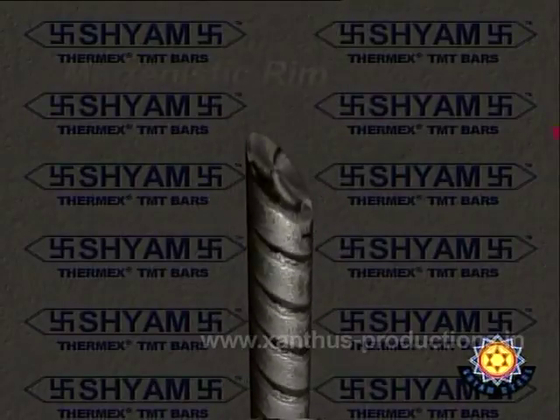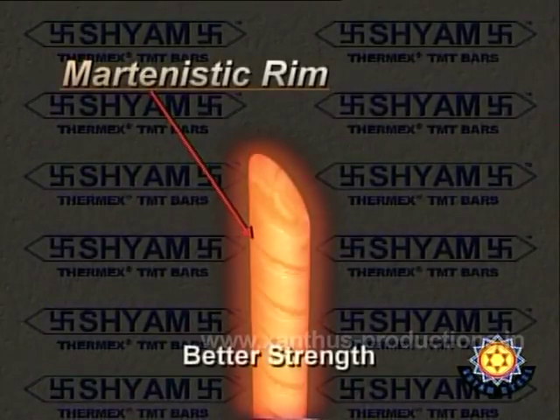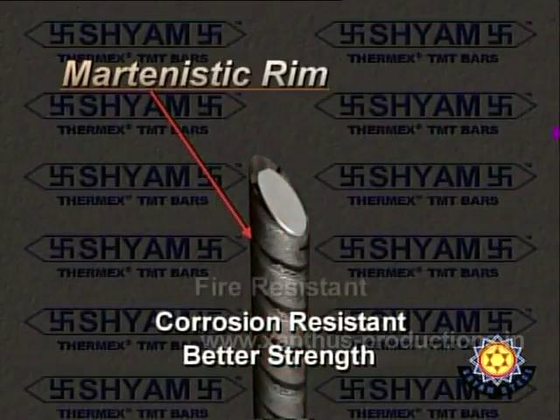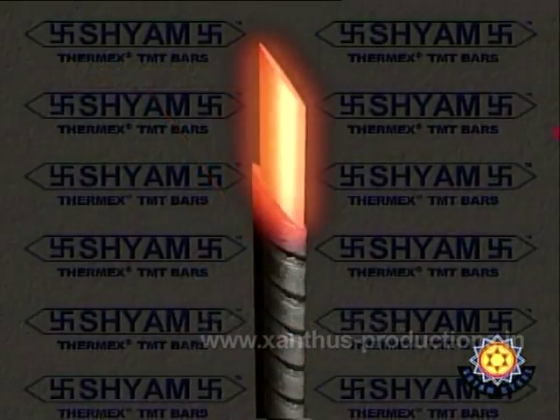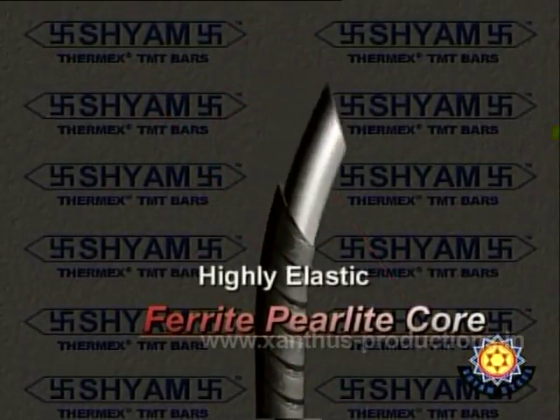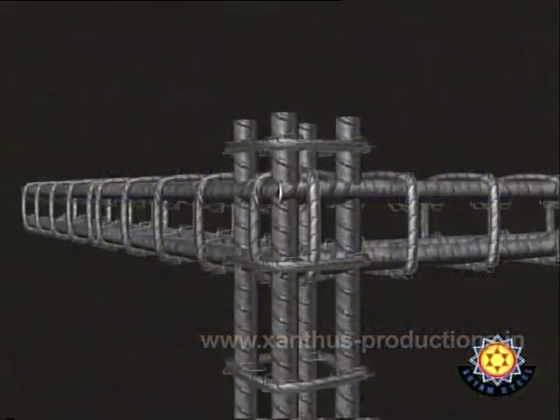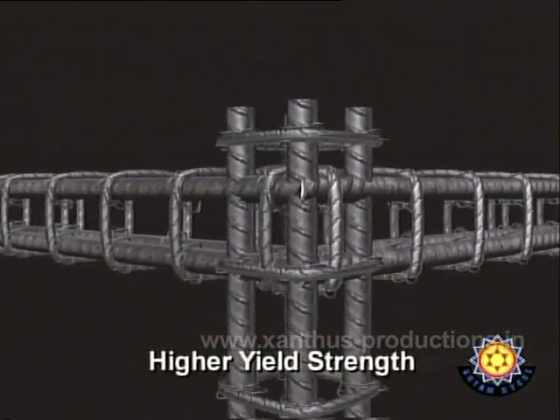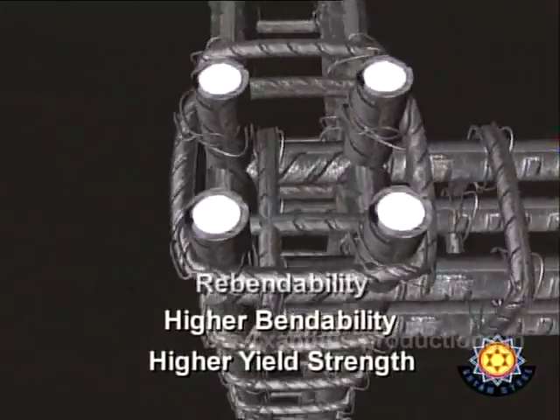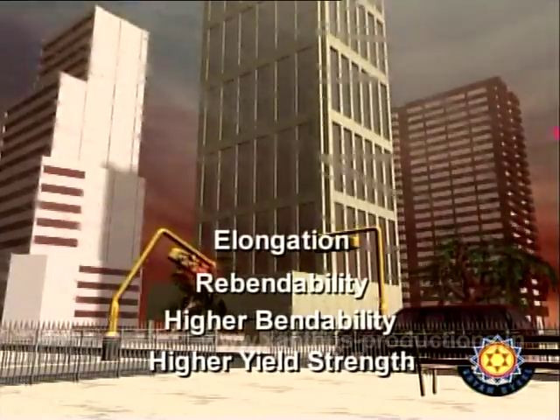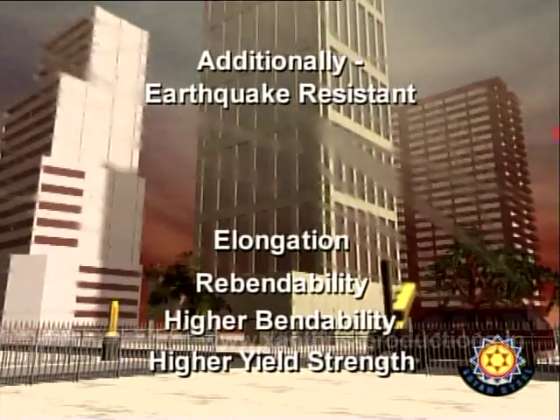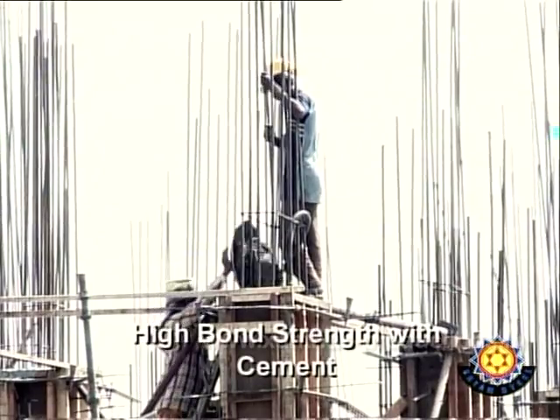The hard martensite outer layer renders the bar with better strength, corrosion resistance, and fire resistance properties, while the softer inner core makes the bar highly elastic. Higher yield strength coupled with high bendability, rebendability, and elongation makes the concrete structure endure higher stress and strain.